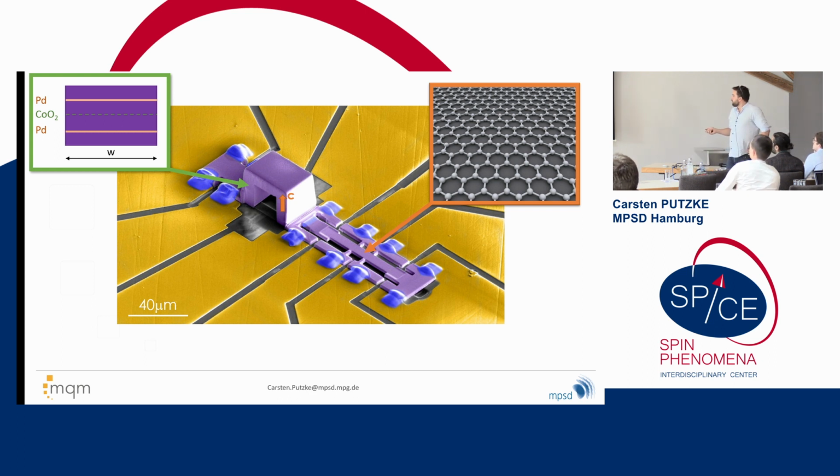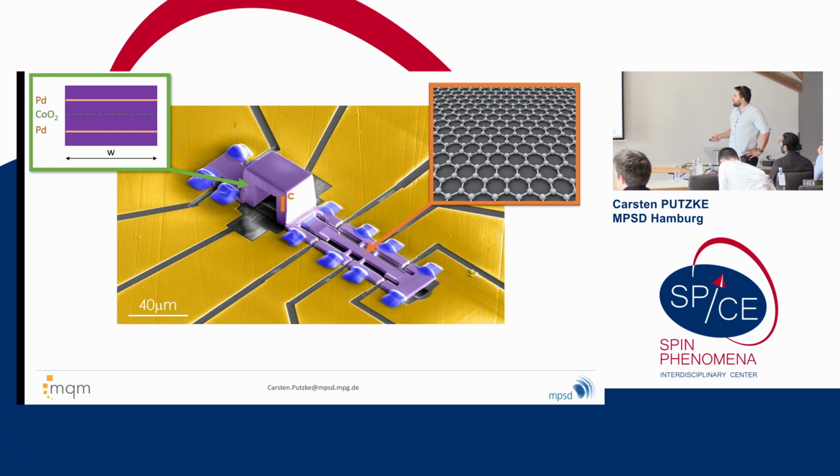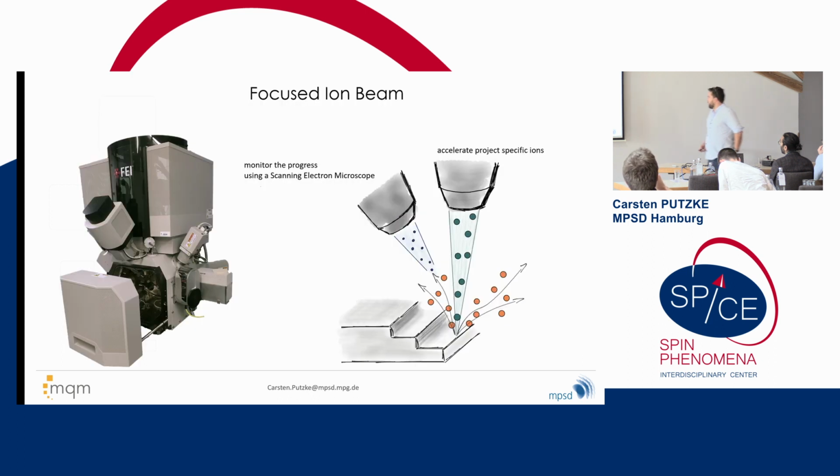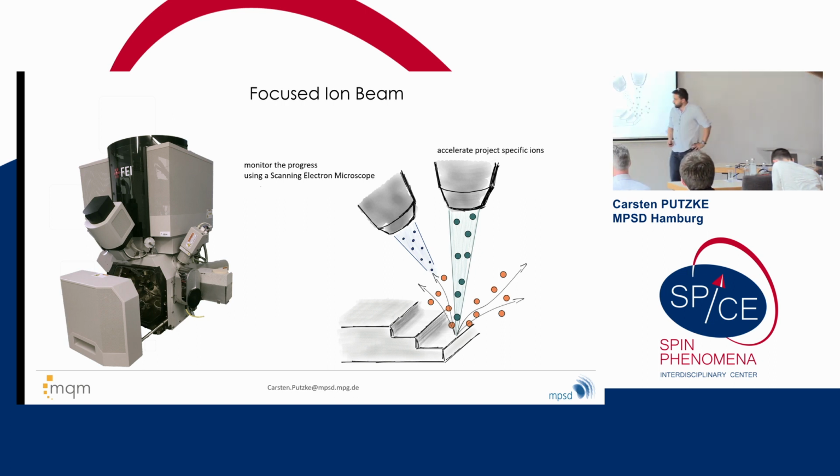And what we do in this case is that we don't limit ourselves in the stacking number, but we limit ourselves in the in-plane dimension of these materials, okay? So we now basically limit the material to a few tens of micrometers, and that's actually on the order of the mean-free path. The way we do this is that we use focused ion beam machining.